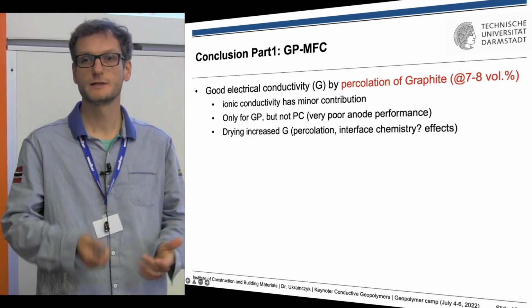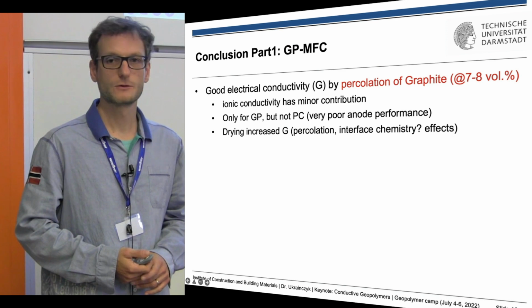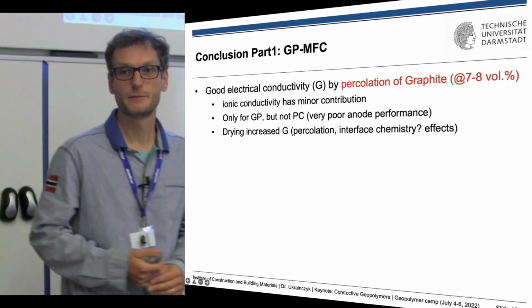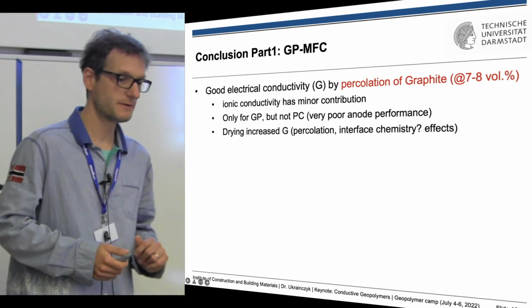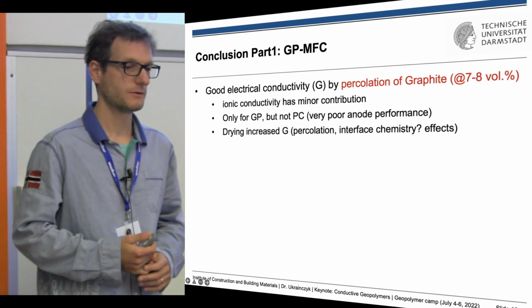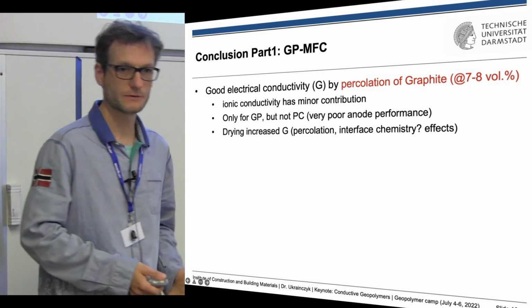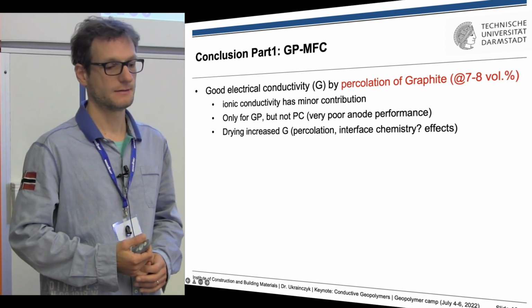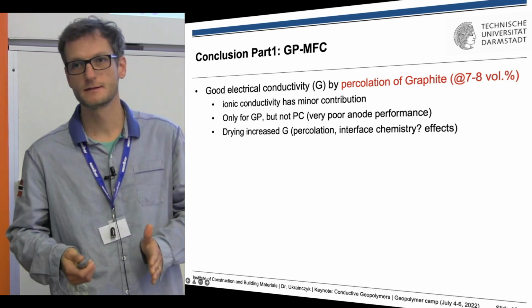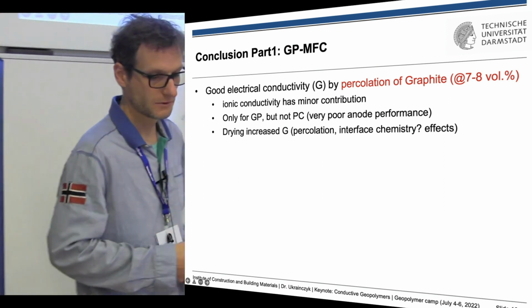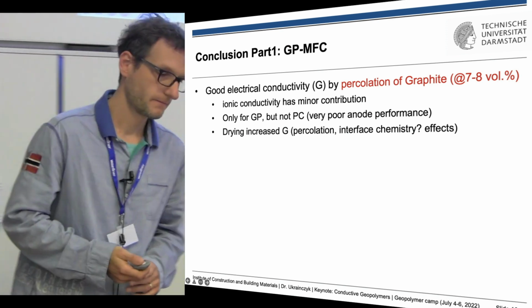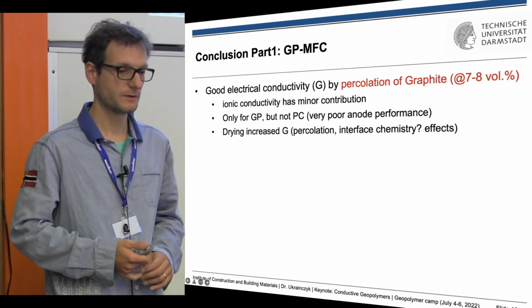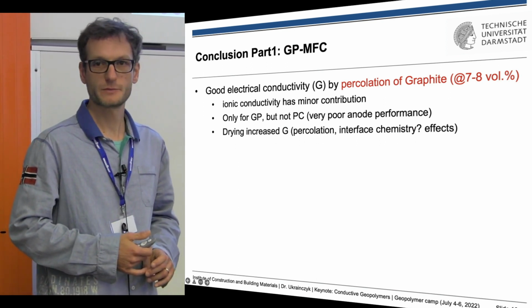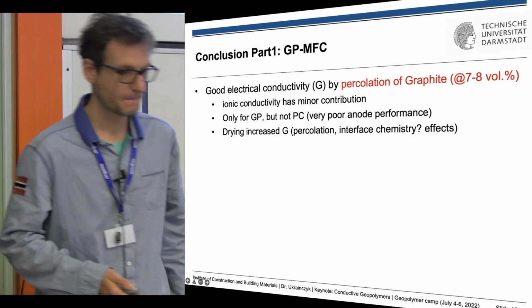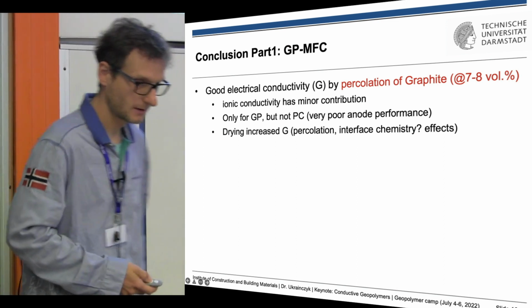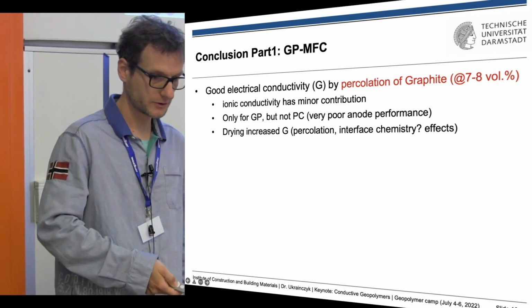And interestingly, by drying, we actually increased the conductivity very much, which we explained by the effect of the porosity, but I'm not excluding also maybe some chemical effects, because there is more interaction, more reaction of the geopolymer for sure when we dry, and probably there is some interaction between geopolymers and graphite, and they could also interact differently by high temperature. So this we also need to study more, but it's very interesting what we observed, that with higher temperature we get better properties, even mechanical. And then next conclusion.